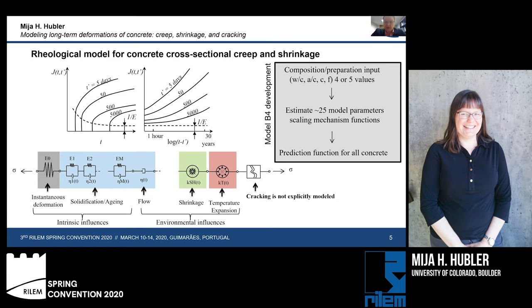As an example here, when we were working on the development of the B4 model, the sequence of calibrating one of these models to develop a prediction function starts with the composition. The composition or the preparation of concrete, such as the water cement ratio, the aggregate content, the cement type, and the strength. So with these few variables and a whole bunch of experimental data, we try to estimate about 25 model parameters that scale the mechanical functions from these rheological equations. This allows us to develop a predictive function that would hopefully work for all mixes of concrete that are related to the data set that we have.